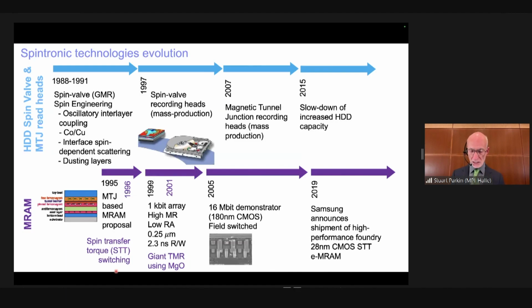So before I come to that, I just wanted to point out that to introduce the spin valve, it took a relatively short period of time, only a few years from the basic discovery of the materials, cobalt and copper, the ability to create artificially engineered structures, in particular the synthetic antiferromagnet, the concept of interfacial spin-dependent scattering or dusting layers. All of these concepts enabled the spin valve sensing device to be introduced by IBM in 1997 and by all other companies within a couple of years. As I mentioned, the basic structures remained the same, but the physics switched from spin-dependent scattering to spin-dependent tunneling in 2007. Today, the magnetic disk drives, whilst they're super important, the ability to increase further their storage capacity has slowed significantly, and alternatives are needed.